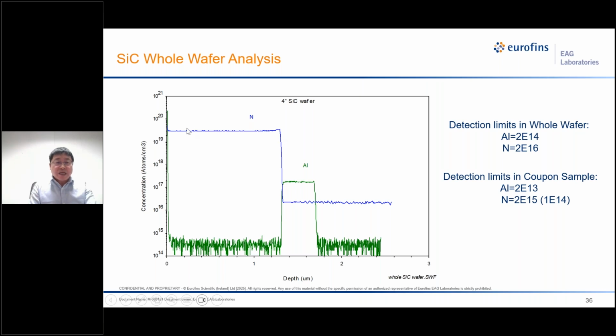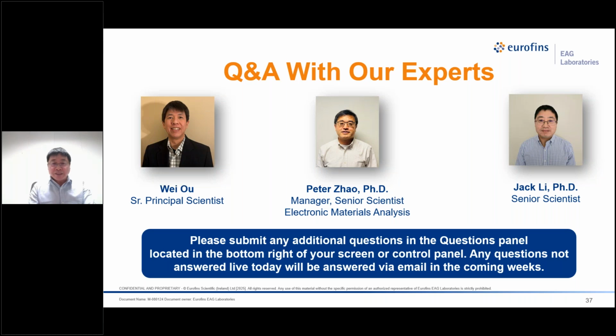So SIMS can measure the concentration of nitrogen and aluminum, and also their shape, and also the thickness. The best detection limit will be obtained from our coupon sample. For aluminum, the detection limit will be 2E13, and for nitrogen, the best is 1E14. With this, I will pass it to Wei for the next session. Wei.